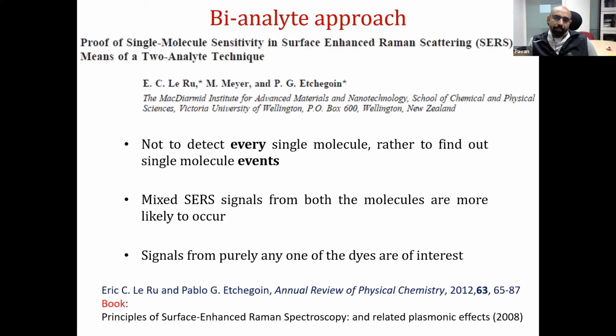The bi-analyte technique, which is a very interesting approach to study single molecule spectroscopic signatures, utilizes a strategy where you do not detect every single molecule, but rather you find single molecule events. Importantly, you will also end up getting mixed SERS signals from both molecules, which are more likely to occur in a particular event. And the signal of interest is purely coming out of the region of interaction.